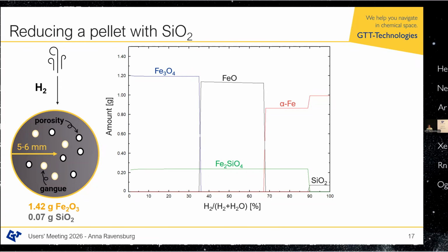in this ratio in order to manage to get iron in the first place, which is relevant for all the metallurgists that are running these processes and have to somehow adjust the ratio of H2 to H2O in their furnaces. But when I look at this, then the 100% conversion with respect to iron is only reachable in this red shaded region, because before that there is also iron in Fe2SiO4. And I need a very, very high H2 to H2 plus H2O ratio in order to reduce this Fe out of this phase and then have it in the alpha iron, and then have SiO2 as well. So this is the metallization degree of 0.87 that I can at maximum reach if I do not go to these very, very high regions.